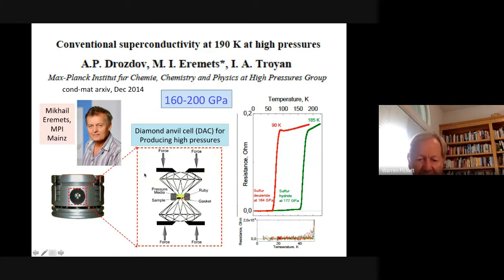Now inside there is the diamond anvil. So what is done is to have these diamonds, because diamonds are the hardest material we have, cut nicely. So when you apply a lot of force to them, they're less likely to break. So you have one here, one here, identical, and they're focused down here, actually a lot like a gemstone, to a small area here, because when you apply force up here to this area, the force it applies down here is multiplied by the ratio of the areas. So you get more force, and when you push these together, more pressure.